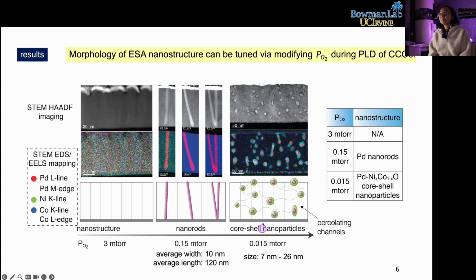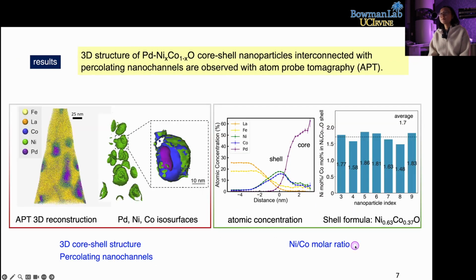From the element mapping, we can see the core part is palladium and the shell part is nickel cobalt oxide. Besides, we can see between these nanoparticles there are very interesting percolating nanochannels. They connect the nanoparticles to form this morphology.